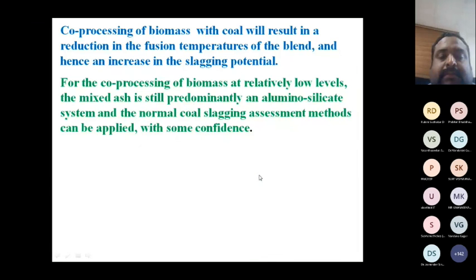So co-processing of biomass with coal will result in a reduction in fusion temperature of the blend and hence an increase in slagging potential. So that is why the restriction, they are saying 5 to 10%. Don't go beyond that. If you go beyond that, you will end up with problems, because biomass has fluxing agents, sodium, potassium. It will bring the coal ash melting temperature lower. So for co-processing of biomass at relatively low levels, the mixture is still predominantly alumina silicate. So cautiously, with some confidence, you can use the slagging prediction method for coal.